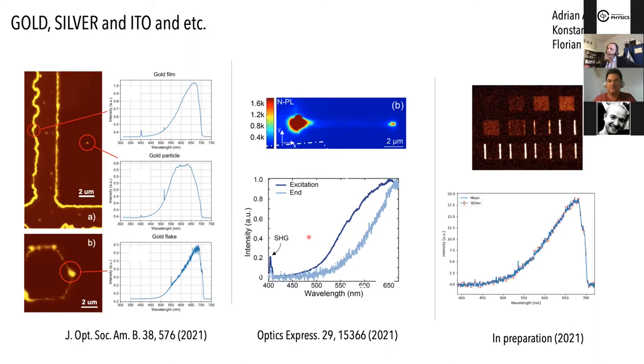So this NPL is also visible in silver. This is, for instance, an image of a silver nanowire. And you can see the decaying curve for silver, which looks very much, qualitatively, like the gold structure. And we also recently found out that this is occurring in ITO. ITO is indium tin oxide. So it's a semiconductor material with lots of electrons, because it is a conductive material. And we found that by structuring the ITO, we have a very strong nonlinear photoluminescence in the spectra. The spectrum that we could observe from this strong ITO response looked very much like the silver or the gold. So it seems to be a very generic effect, which occurs as soon as you can bring the electrons to an elevated temperature with a femtosecond pulse laser.